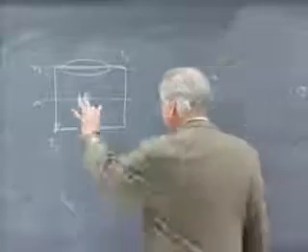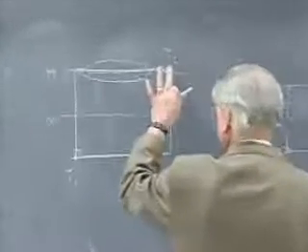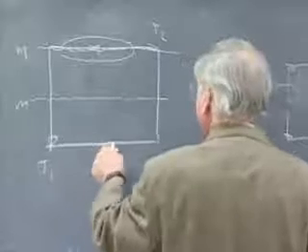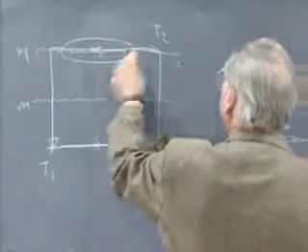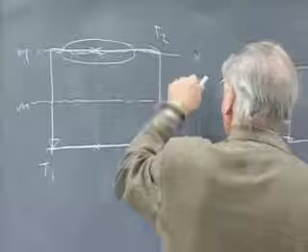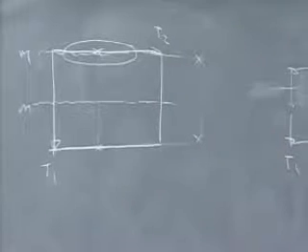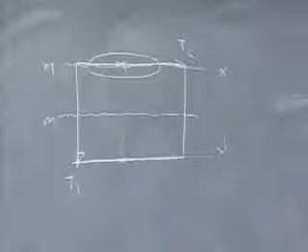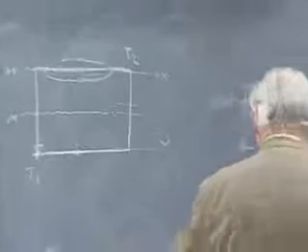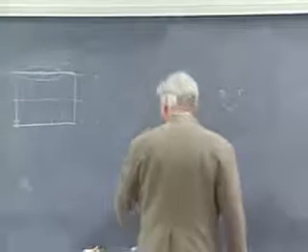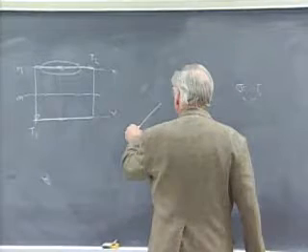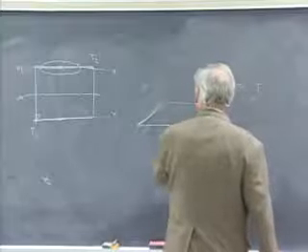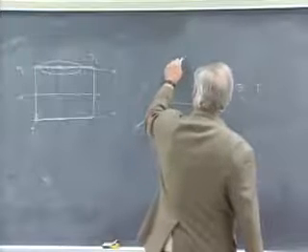Okay, I can pick this net up, slide it parallel to T2, and as long as I put it down so that this is the lattice point in the next layer up, that will be a legitimate placement of the net, because all the mirror planes are simply slid into coincidence with one another. So if I sketch that thing in 3 dimensions, this is the base of the cell, and it has a rectangular shape, and the third translation goes up at an angle.